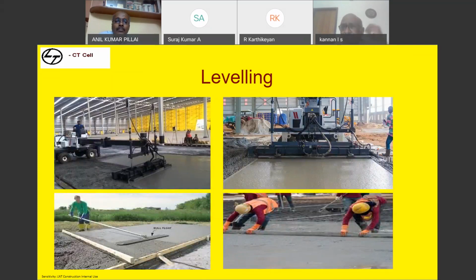Nowadays, laser screed is also available, where undulations in concrete can be minimized. That is also possible, where your slump of concrete needs to be around 140 to 150 millimeter, and you need to place something around 40 cubic meter per hour. That's the requirement of concrete needed for the leveler and screeder. Then only will it be able to place and compact the concrete well. Here you can give a level through the laser, where the machine can do a compaction with 2 to 3 millimeter variations, within the allowable tolerance.